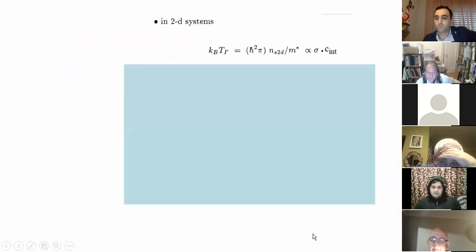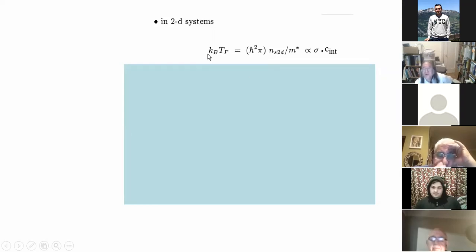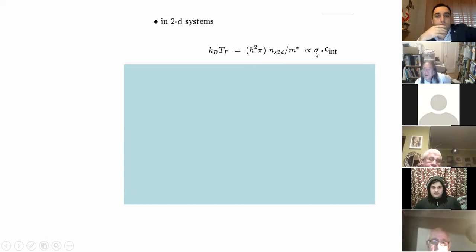Okay, so we wanted to make it a little bit more quantitative argument. This number of superconducting carriers, or number of charge carriers divided by the mass, is a property you can convert to a typical energy scale called the Fermi temperature. This is the most fundamental energy scale of the metal, and it shows the kinetic energy of the charged particles in the metal or superconductor. In the case of two-dimensional systems, this is directly related, so we just need to know the conductivity and crystal structure, and you can get this property very easily.